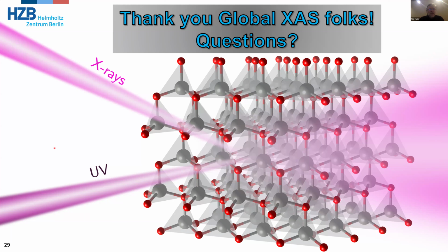So are you specifically trying to look at that effect at all, or is that just another level of challenging experiment? No, we have not done this. Actually, if you look at the literature, there are quite a few pump-probe XAS experiments on zinc oxide nanoparticles. There are a couple at least, and you can look into it. The interpretation is actually different there. They actually do talk about trapping of charge carriers. So it may actually influence, I suspect, quite a lot if you go to very defective systems. Okay. Thank you.